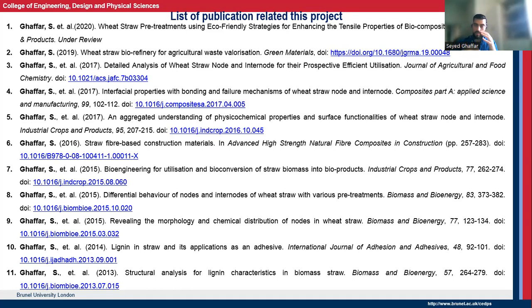So as I showed you, we have internode and node. Each of these anatomical sections of the wheat straw has specific chemical characteristics, physical characteristics, and mechanical properties. So when we are thinking about a biorefinery, we have to be specific and, according to these characteristics, define an application with these parts. And we found during our study since 2013 that for biocomposite production it is best to use only the internodes and not nodes because they are a defect, especially when they have very weak tensile strength.